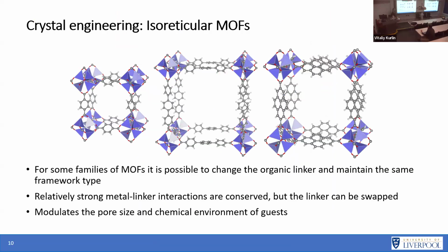So this leads us on to actually trying to engineer these materials a little bit more. To do that, we do something called isoreticular chemistry. This is where we keep our inorganic units, so we keep our metal cluster the same, but we change the linker that we have inside the framework. So this here is the representation of that MOF-5 structure that we saw before. So we've got our zinc clusters coordinated by our benzene dicarboxylate linkers.